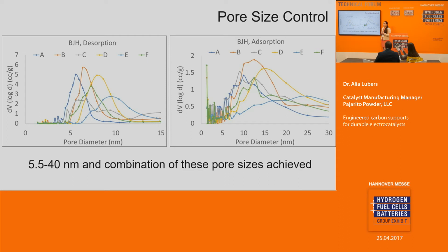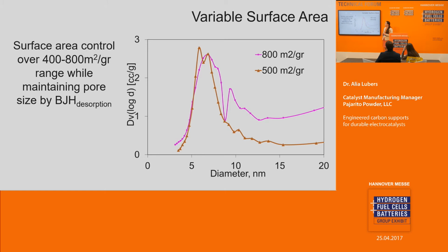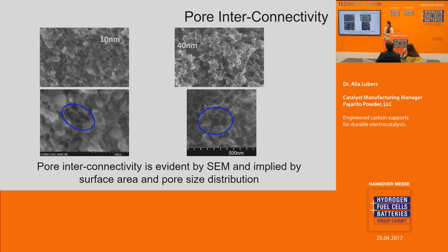Here are some pore size distributions of some of our materials, and we have been able to produce quite a wide range, between 5.5 to 40 nanometers of pore sizes, and we can have mixtures of compositions in between those sizes as well to various compositions. We can also increase the surface area without compromising the size of the particles or of the pores, at least not to a great degree. Although our pores are not continuously interconnected, we do have a high degree of interconnectivity if you require that for your catalyst support.